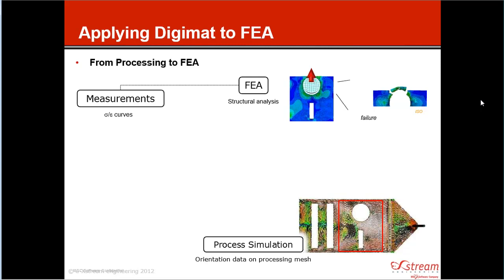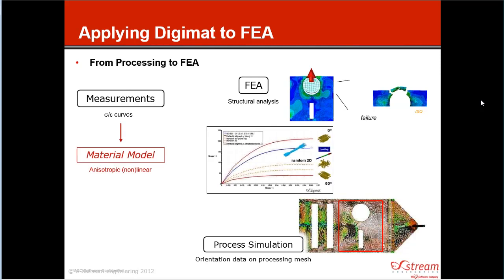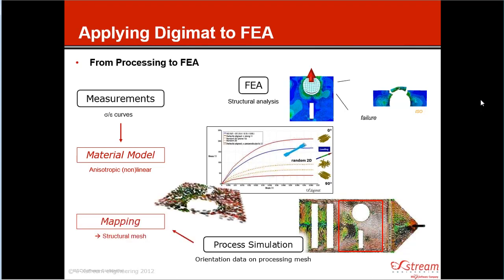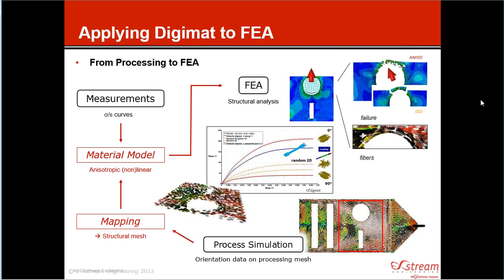So what Digimat allows you to do is take the information coming from your material supplier, so your stress strain curves. You can then build an advanced nonlinear anisotropic material model, so one that takes into account the local fiber orientations. You can then take the information coming from your injection molding simulation and map that over to your structural analysis. And this step is important here because that means that you don't have to have the same mesh in your injection molding simulation as you do in your structural analysis. You know, typically you have very different mesh parameters in your injection molding simulation versus your structural analysis. So you can map that information over. You can then bring that all into your finite element analysis to get a more accurate prediction of how your part behaves.